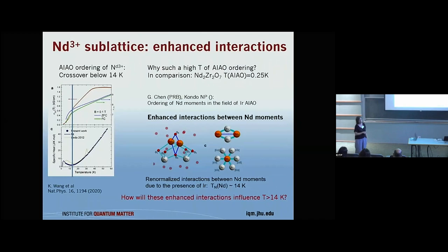So is there evidence for that? So there is. Neodymium has a lot of experimental issues, and now, after I looked at this, I know where to look. There are some papers, especially early ones, where as soon as it becomes stoichiometric, it becomes very metallic. There is a paper on Nd2Ir2O7 in PRB from a few years ago, where they observed in magnetic susceptibility a very tiny splitting between zero field and field cooled at pretty high temperatures, like 100 K, which I never believed before, but now I think we should look back to it.